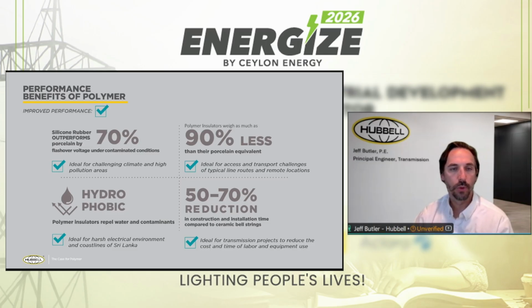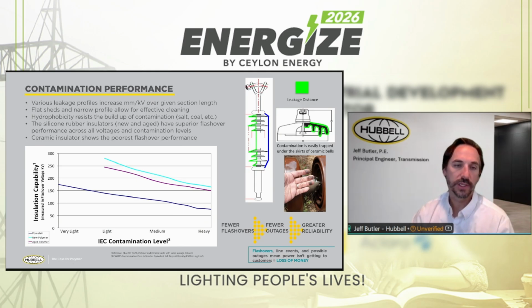So let's go into a little bit more detail of what I'm talking about. So this was the test or the study that we did where we were looking at contamination performance. It may be a little challenging to make out this graph, but the line at the top is a new polymer insulator. The line in the middle is an aged polymer. That meant that we put it through an environmental chamber for the equivalent of 10 years of life. Put it through, I can't recall the exact hours, I think it was 500 hours in a salt fog chamber, but we basically wanted to demonstrate that even not new, a polymer insulator can still perform well, and that speaks to the hydrophobicity breakdown or the aging of the polymer.